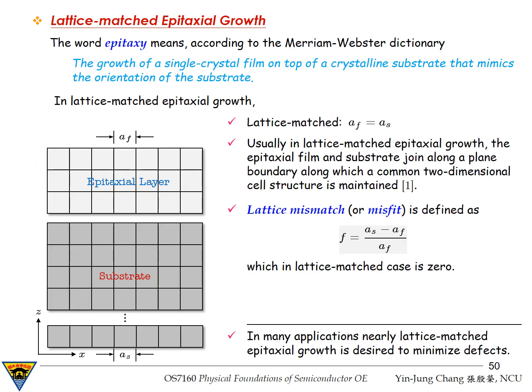Let's begin by understanding the word epitaxy. When we grow an epitaxial film on top of a crystalline substrate, the atoms in the film attempt to align themselves with the periodic structure of the substrate. The word epitaxy, as mentioned on this page, means the growth of a single crystal film on top of a crystalline substrate that mimics the orientation of the substrate. In ideal lattice-matched epitaxial growth, the lattice constant of the film, denoted by a_f, is equal to that of the substrate, denoted by a_s. In this case, the two-dimensional unit cells at the interface are continuous. There is no strain at the boundary, and the crystal structure transitions smoothly across the interface.